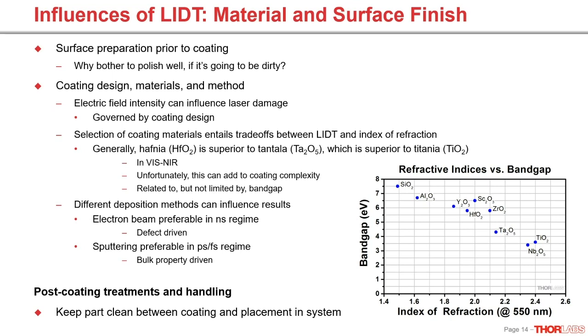And then there are a number of things to take into account with the coating. First, you're going to want to look at the design. Something like electric field intensity is often overlooked, but you can dramatically change the laser-induced damage threshold of an optic by manipulating the electric field intensity. Depending on the coating design, your electric field is going to have peaks and troughs as it propagates through the coating. And if you have those peaks occur at an interface, whether that's between two of the materials, high and low, or low and medium, or medium and high, that's a negative.